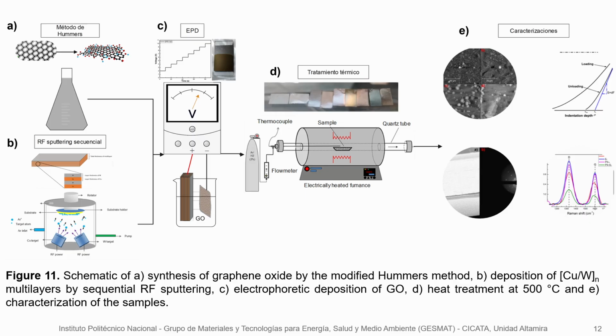We synthesize copper tungsten multi-layers with different thicknesses, from 2, 5, 10, 20, and 50 nanometers of individual layers. Then we deposited electrophoretically the graphene oxide onto the multi-layer in the different samples, and then a thermal treatment was applied in order to reduce the graphene oxide coating to reduced graphene oxide. Then all the samples were characterized by AFM, nanoindentation, high resolution transmission electron microscopy, and by Raman spectroscopy.